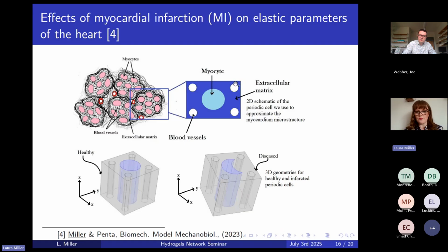So this is my structure, and I'm assuming this is, again, very basic, but a very simple structure for the healthy myocardium. So I have an intact bundle, an intact compliant ECM, intact compliant myocytes, and nice channels. In my diseased case, I have created something where some of the myocytes have unfortunately become too damaged beyond repair, and therefore have had to be replaced by the ECM stiffening into a hard collagen-rich scar. So that's what I have here.